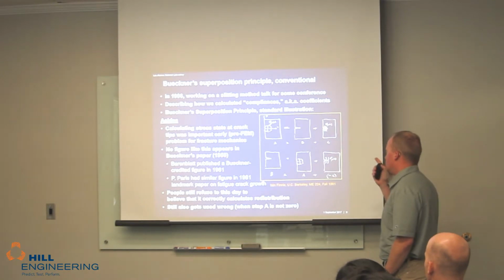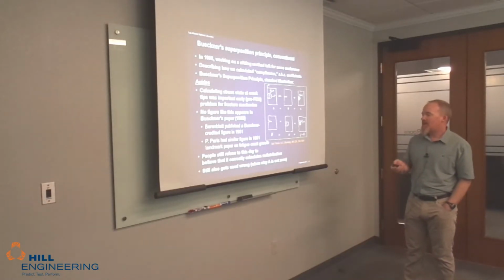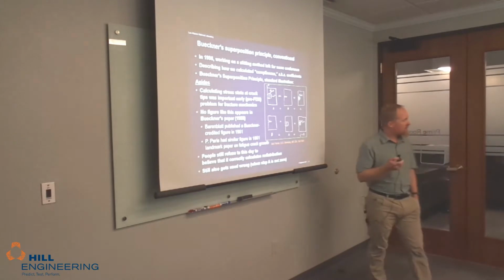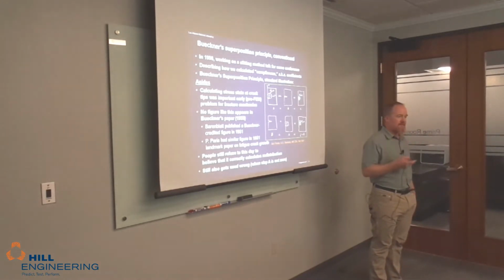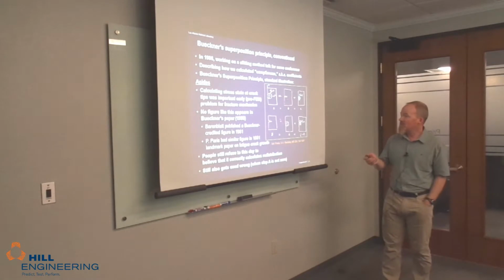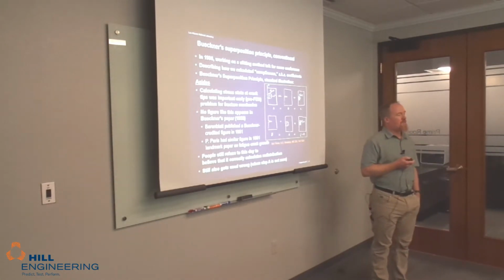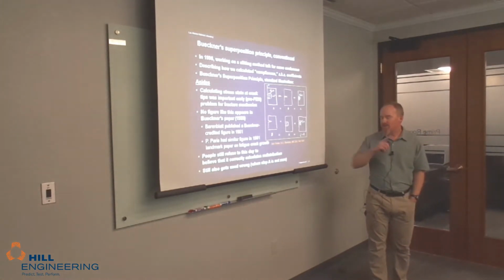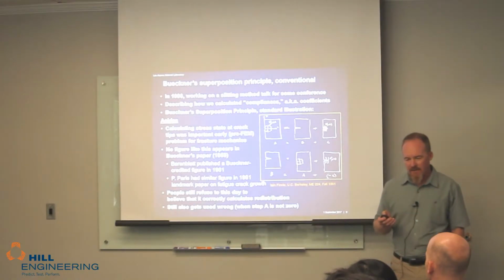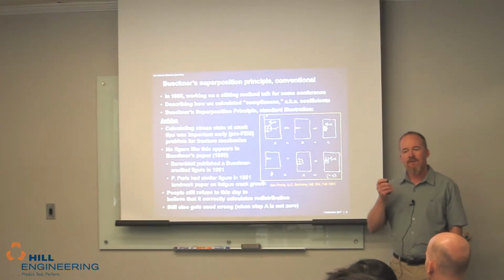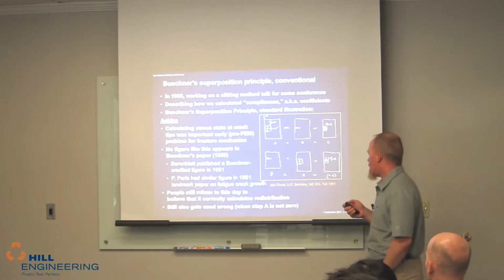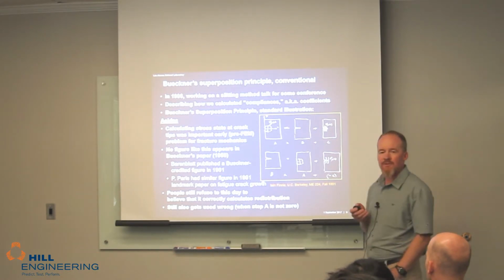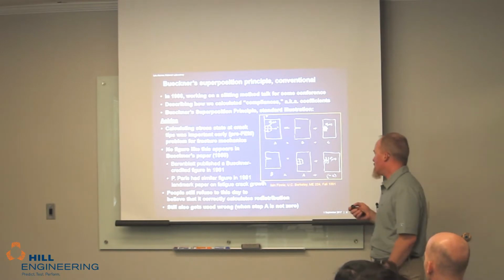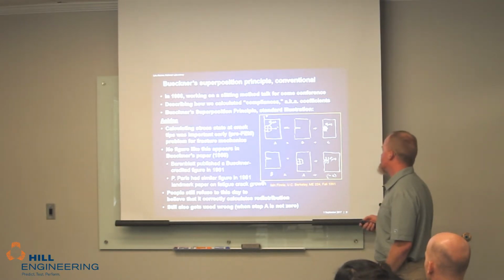As another aside, there's a very similar figure to this in Paul Paris's paper on fatigue crack growth. So Paris's law, da/dN is C delta K to the n, very famous paper. He's got a figure like this he used to calculate that delta K for fracture mechanics. For fatigue crack growth, if you don't know the story, and I won't spend too much time, that paper was published in the engineering alumni newsletter for University of Washington because nobody would publish it. And it was a really quite brilliant piece of work.